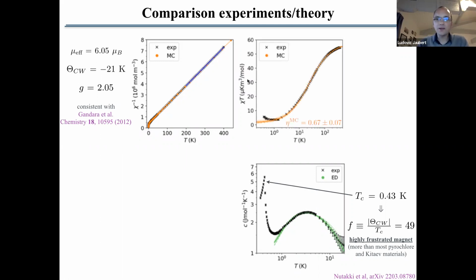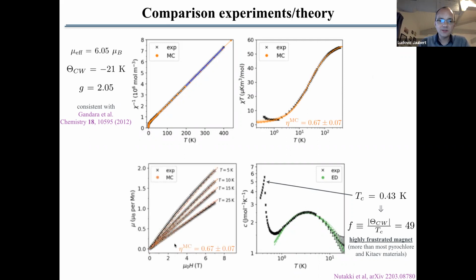And then we have compared the susceptibility, so it's Chi versus temperature here. We have compared the susceptibility and the magnetization in the magnetic field with Monte Carlo simulations. We use Monte Carlo because, as we discussed before, we have this nice J1, J2 Hamiltonian, and we have manganese ions which have strong magnetic moment, and are isotropic. So you can use classical Heisenberg spins there.